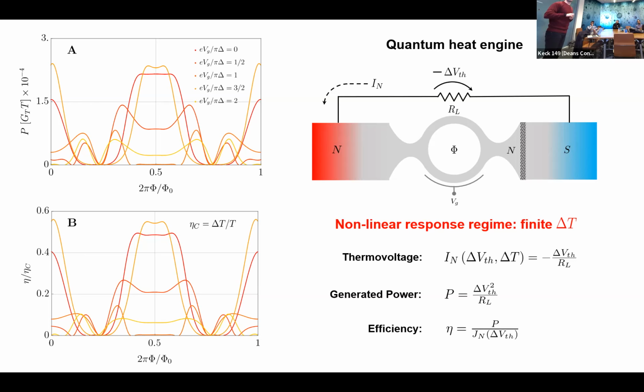To the left, I plotted the results for these performance quantifiers. In panel A, we have the power, and in panel B, we have the efficiency normalized with respect to the Carnot efficiency, both as a function of the controlling parameters, namely the magnetic flux and the electrostatic gate potential. Here you can notice two important things. The first one is that you can control these performance quantifiers by just applying and controlling an external parameter, which is very important, at least from an experimental point of view, because this gives you the possibility to change these thermodynamically important quantities simply by acting on a tunable parameter. The other very important thing, from panel B, is that our efficiency can reach very high values, of the order of 55% of the Carnot efficiency.